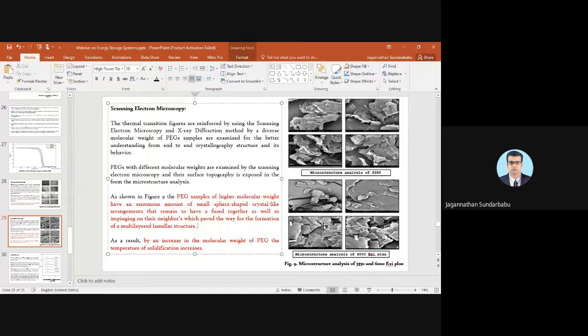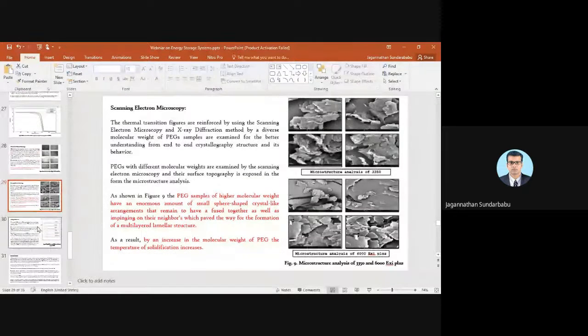From the figure you can see this is called fusing, or you can say impinging on the other neighboring particles, right? That could pave the way for the formation of a multi-layered lamellar structure. You can see the lamellar structure over here in the scanning electron microscopy analysis. As a result, it is clear that with an increase in the molecular weight of the PEG, the temperature of solidification increases, the same criteria which we have seen in the differential scanning calorimetry, right?